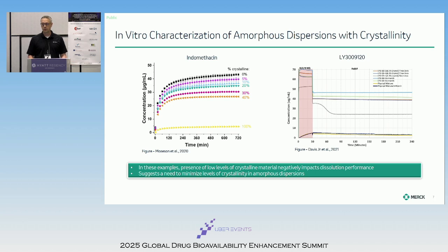And there's been numerous reports around this, looking at dissolution performance, trying to assess what occurs. And across most active ingredients, you tend to see that as you increase crystalline content, you decrease the dissolution performance, which should, in theory, drive a negative impact to the oral bioavailability of the product. And we know that, at least in the most extreme cases of fully crystalline material, the performance will be different than what we have with an amorphous dispersion. And so we need to make sure that our amorphous dispersions are controlled to minimize the extent to which we see crystalline content in the drug product.